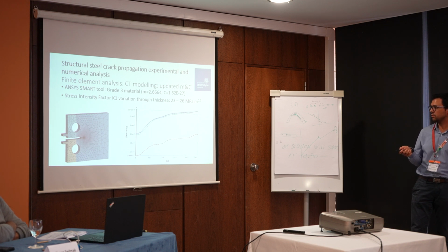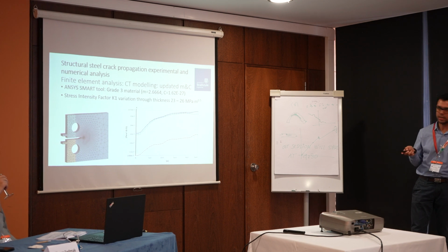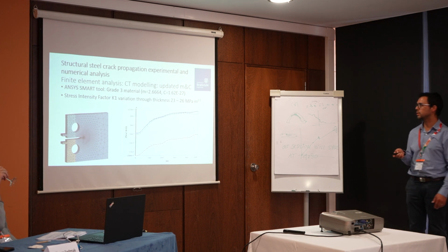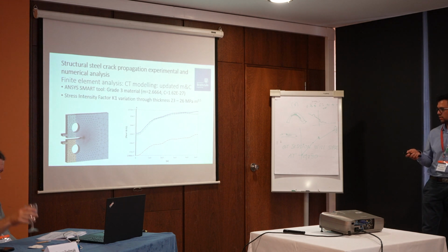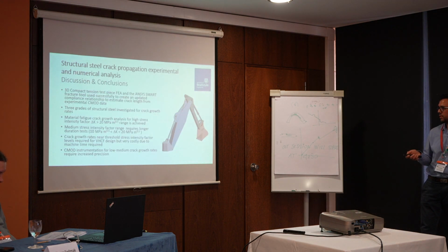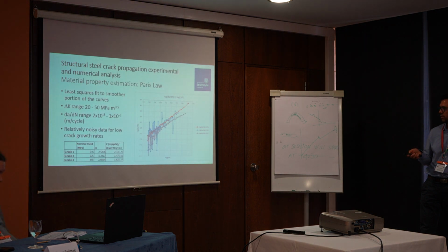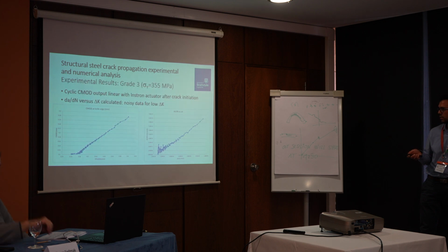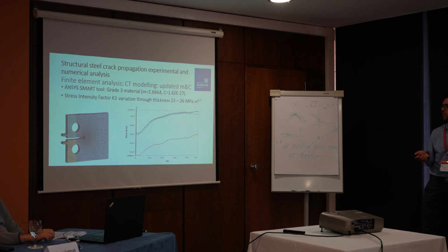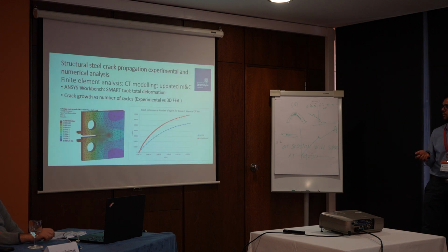And here is something that we can highlight, that the stress intensity factor goes between 23 and 26 megapascal square root of meter, which is something a little bit similar to what we got in the beginning of the sample data, such as the grade 3 in this case. So sorry for scrolling up.